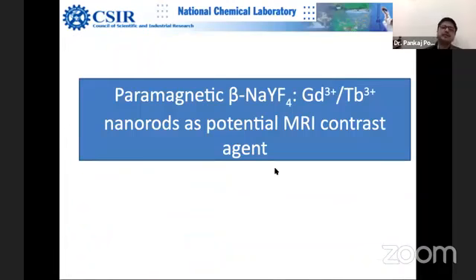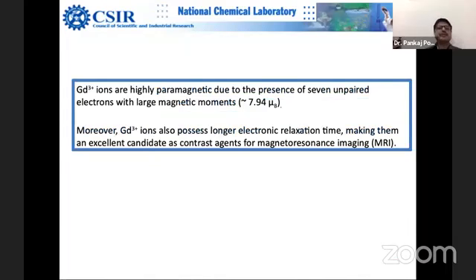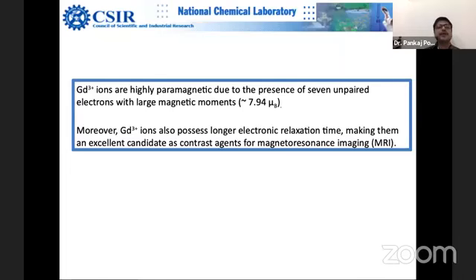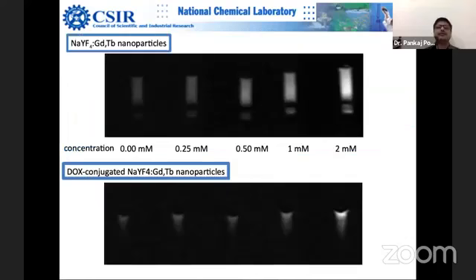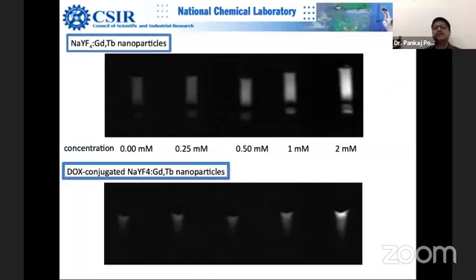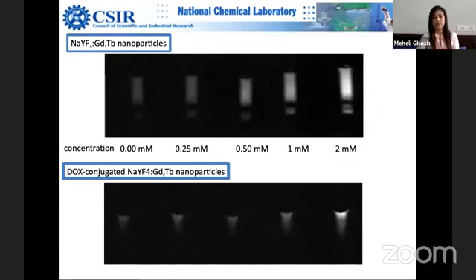We took the effort to look at MRI signals of the system because gadolinium has a very strong magnetic moment of 7.94. There is no exchange interaction because gadolinium ions are lightly doped, but it has a strong paramagnetic signal. We could see that these particles indeed show a very nice magnetic contrast enhancement in the MRI signal. Of course, there are plenty of details — we did NMR and all the parameter studies. This is just a sense of what we did.